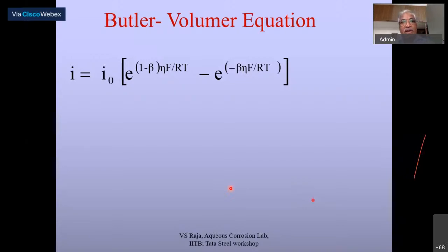And the great guys, Butler and Volmer, these two guys, formulated the equation. There are again derivations. You want to read the derivation, you can look at Bockris and Reddy's book. You will have a nice illustration of how to derive the equation. So the current that you are going to measure in the system is related to what is called the overvoltage, that is the deviation from the equilibrium, and of course a symmetry factor. And you can calculate the excess current density, right? So the excess current density, the overvoltage, and this factor that you see here are related